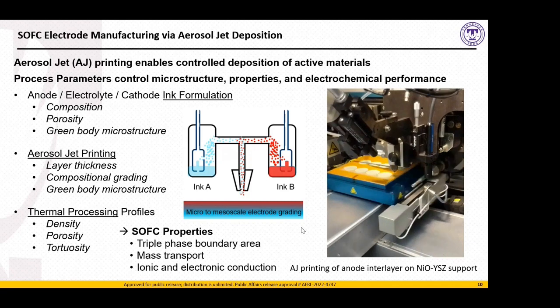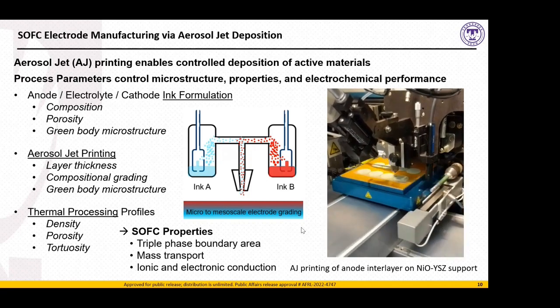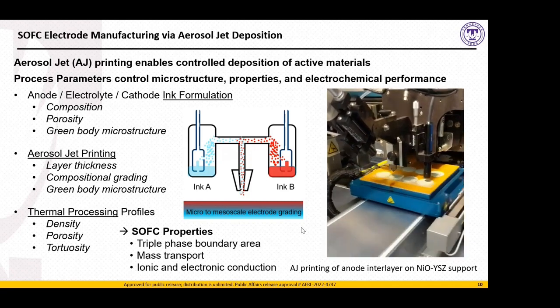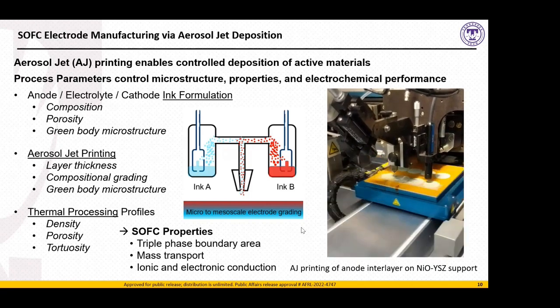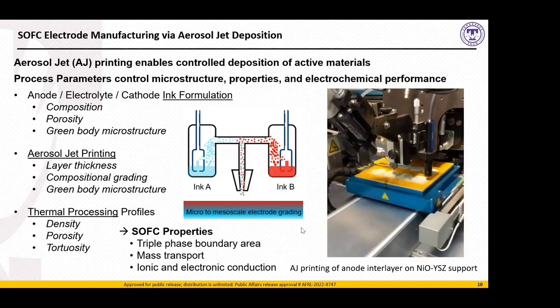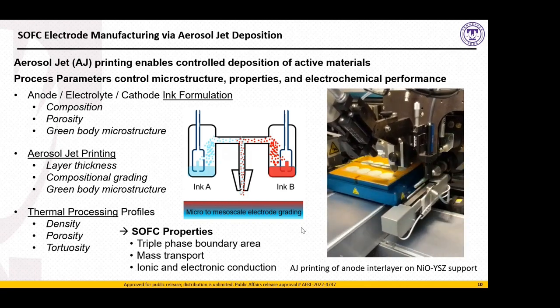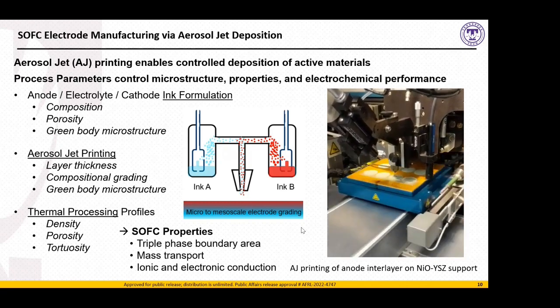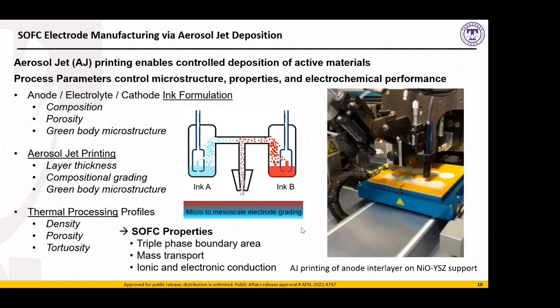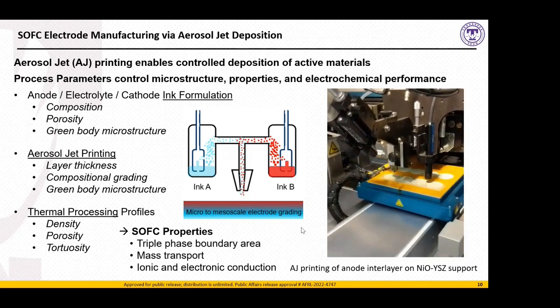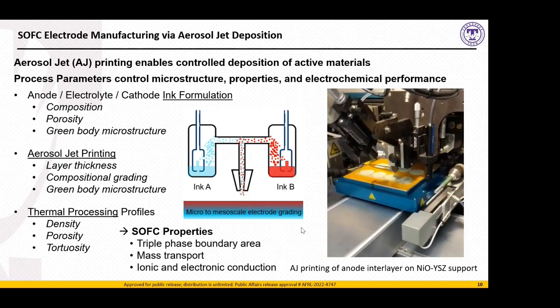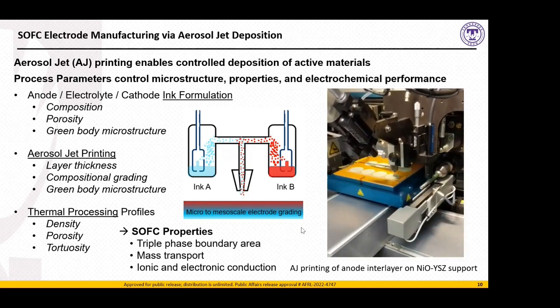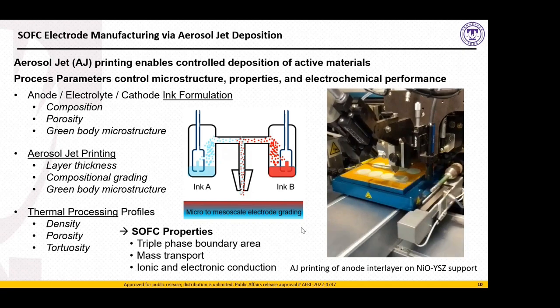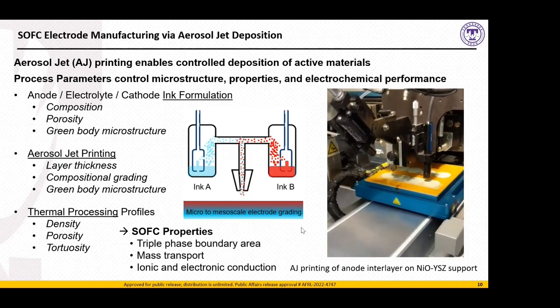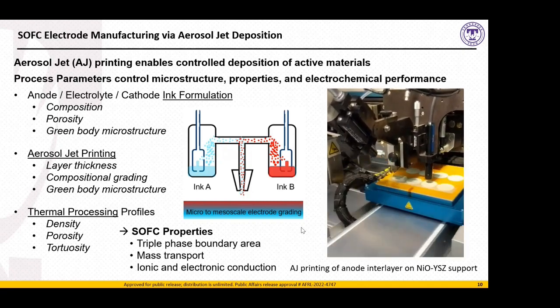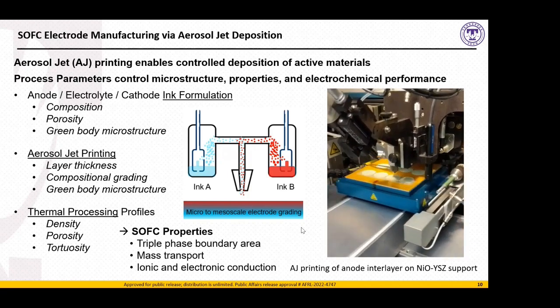With aerosol jet printing, we get really fine control over the layer thicknesses, the thickness of the electrolyte and the electrodes. It also introduces the ability through this 3D printing process to add compositional gradation, where we have a smooth gradation from one material to the next. And you're probably already thinking ahead, and you can see here the possibility of softening these interfaces between the respective parts of the SOFC.